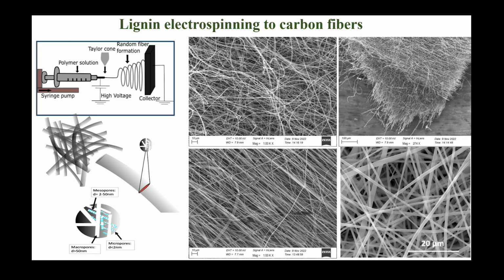And so over the years, we've also been looking quite a lot at this technique, and we've been producing fibers that are completely disordered, more aligned, or we can even have rotating drums and align them in different directions where we gain a bit in mechanical properties. Now, we are not doing these carbon fibers to compete with structural carbon fibers that are made from PAN, because many people have tried, and my personal opinion is that nobody will ever succeed to beat polyacrylonitrile. But we are doing this to create flexible, freestanding, conductive carbon mats from more sustainable precursors for energy storage and